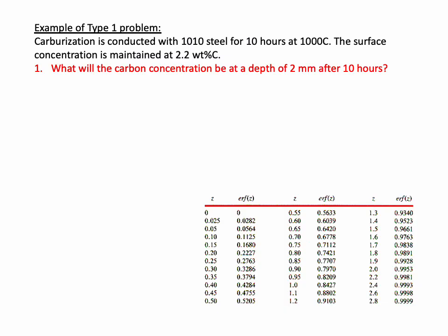All right, so let's set this up then. First, I'm going to need to know D. So D at 1273 Kelvin is equal to D0, 2.3 times 10 to the negative 5, e to the minus Q, which was 148,000, divided by R, 8.31, times T, 1273.